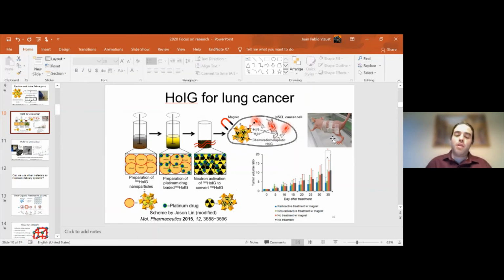So magnetite is a more effective magnet. That's why we're trying to use the magnetite and then build a MOF around it to have the holmium. That's the reason. And of course, the magnetite has to be very small, and the coating around that magnetite also has to be very small, so we can use it.